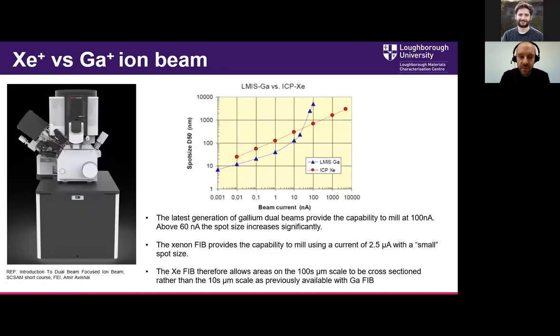And this really led to this question of, can we get to deeper features and can we get more statistical significance? It has led people really towards xenon plasma FIBs. So gallium sources are currently limited up to around 100 nanoamps, at which point the source size becomes very large. So that instead of milling a nice neat cross section, we mill quite a big hole. It's not very tidy. Whereas with the xenon sources, we're able to cut at much higher currents, all the way up to 2.5 microamps, with a relatively small spot size. What we do pay for with the xenon FIB is that at low currents, we don't have as small a spot size as we would with a gallium ion beam system.